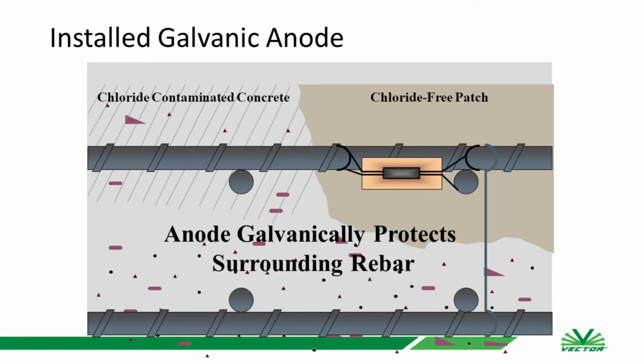One way that we help to prevent against that ring or that halo effect is the use of galvanic anodes. Galvanic anodes, the ones that we use, you're going to be using zinc. Zinc is much more electronegative than reinforcing steel. So anytime you put two dissimilar metals together, the more active metal will corrode first, rather than the corrosion happening at the more noble metal.